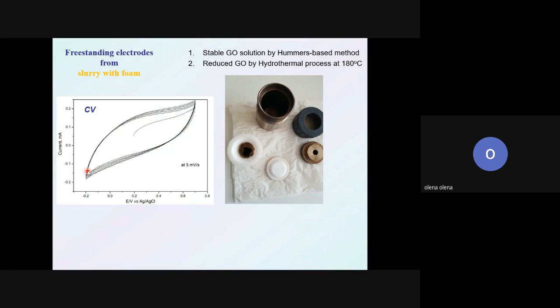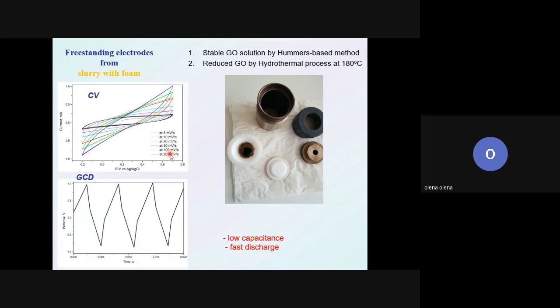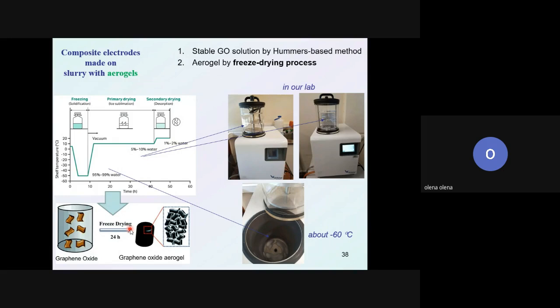And surprisingly, we have a very nice, almost rectangular CV at very low scan rate. It looks perfect and stable. As you can see, this is 5 cycles. However, when we start to increase our scan rate, typically the area should increase, but the area did not increase and just rotated. That means that the material is not good for this electrochemical study, and the charge discharge, as you can see, is also a very fast discharge. So we conclude that this method is not the best, and we start to think about aerogels.